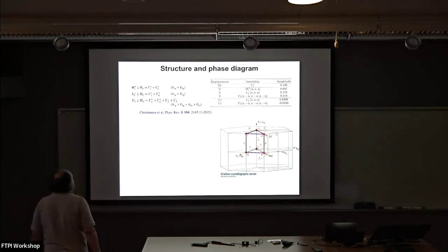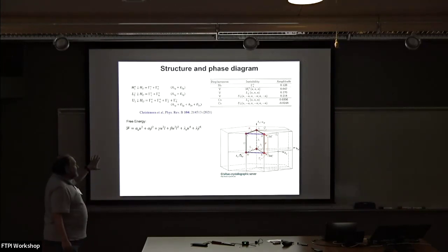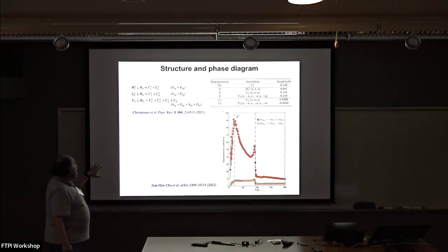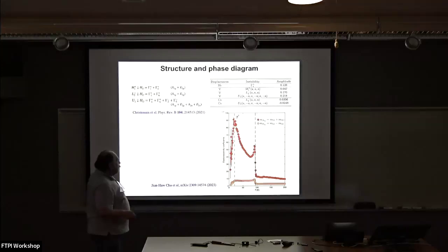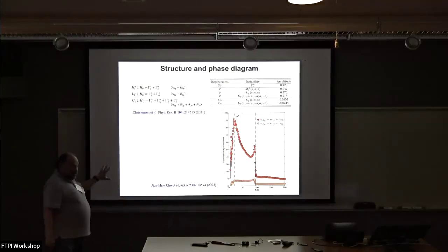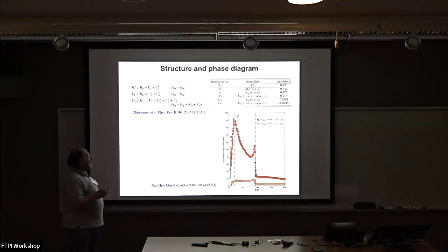Now, by doing this Raman study, I'll skip that. Well, I'll come back to this plot, but let me give you the result. By doing the Raman study, and I'll show you why, we very convincingly showed that we are dealing with this fully symmetric representation. So the true bulk ground state doesn't break any symmetries.